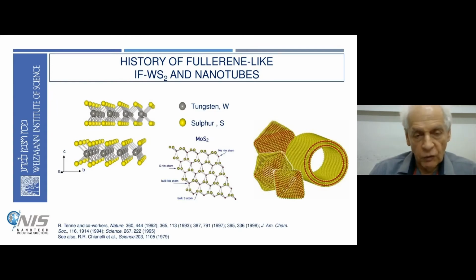The example shown here is tungsten disulfide or molybdenum disulfide, again a layered structure material. It's made of layers, here the tungsten atom, here the yellow sulfur atoms. The layer is complete with three atomic layers, tungsten or molybdenum sandwiched between two outer layers of sulfur. So this is one layer, and the second layer on top is about 6 angstrom above it. Again, the interlayer forces are very weak.